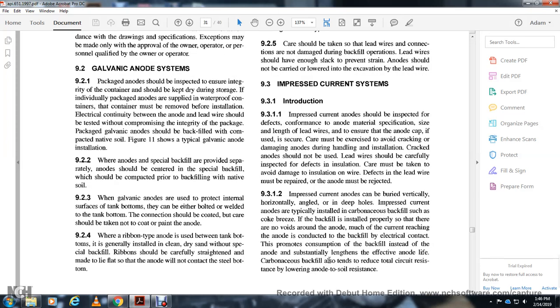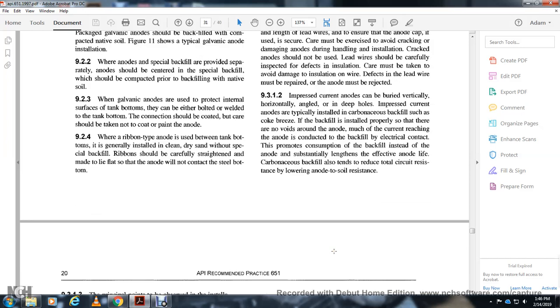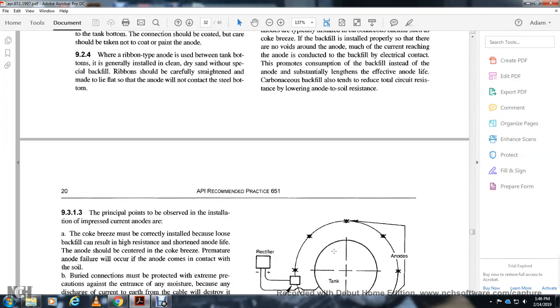Impressed current anodes may be installed vertically, horizontally or at an angle in deep holes. The anodes are typically installed with carbonaceous backfill such as coke breeze. The backfill should be installed properly so there are no voids around the anode, so that current reaches the anode through the backfill and there is electrical contact with the surrounding soil. Carbonaceous backfill also extends the effective anode life and tends to reduce the total circuit resistance by lowering the anode to soil resistance.